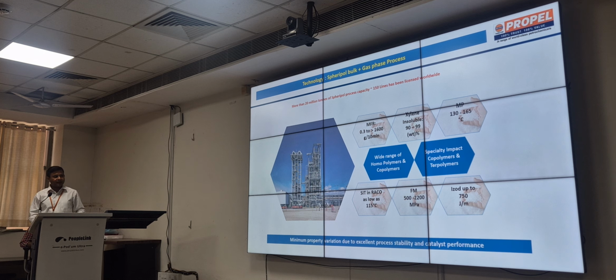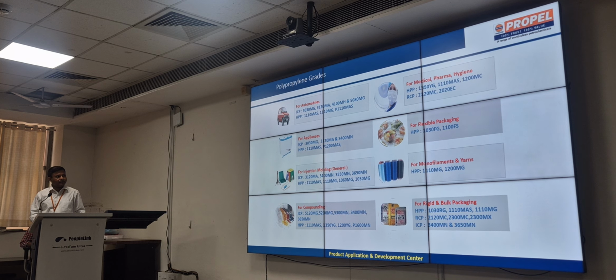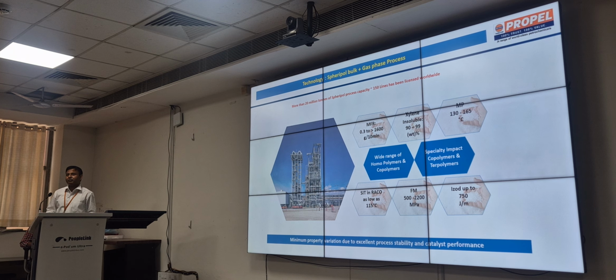Sealing initiation temperature for random copolymer is up to 115 degrees centigrade, flexural modulus 500 to 2200 megapascal, Izod up to 750. The challenges come for the domestic manufacturers who produce the ICP, in the ethylene propylene rubber distribution. We generally follow the easiest route, increasing the C2 content much higher to get higher Izod impact strength.